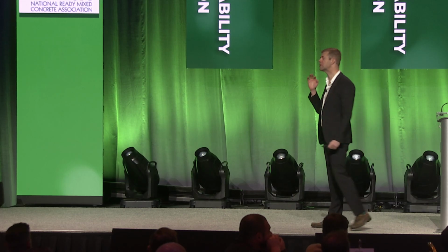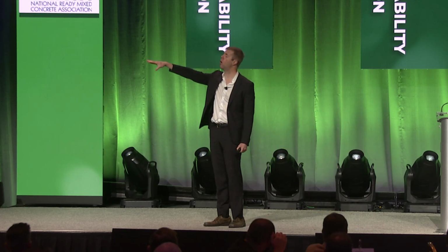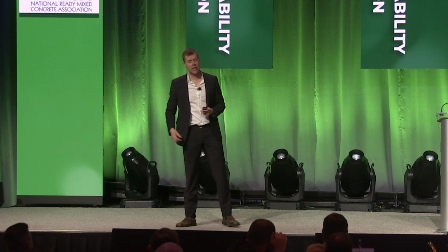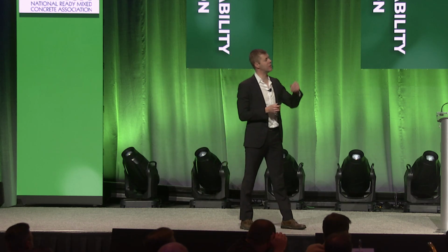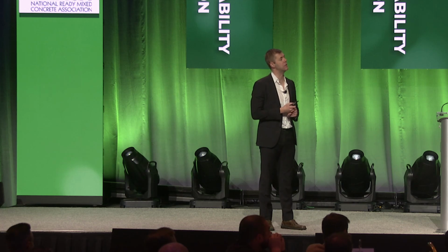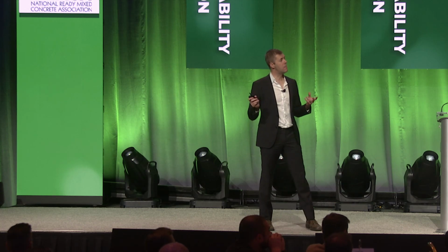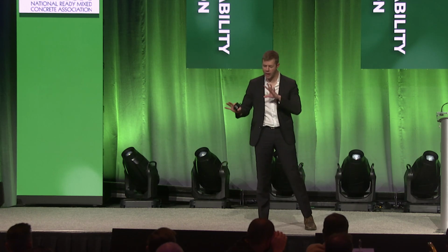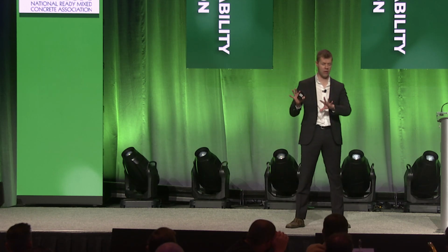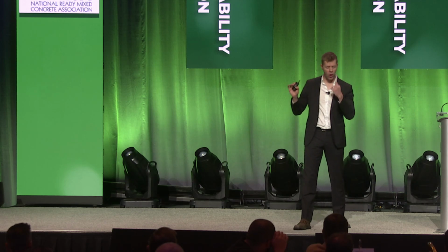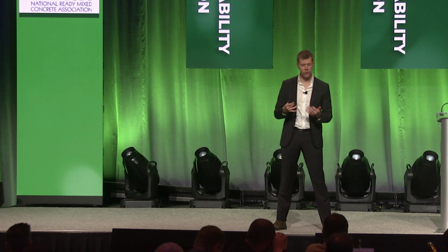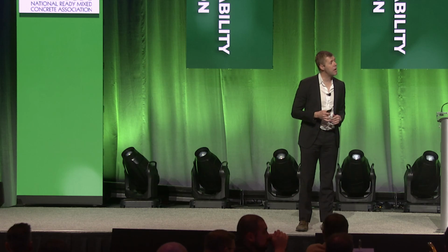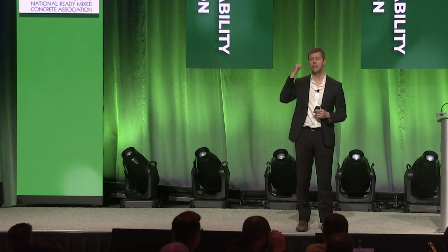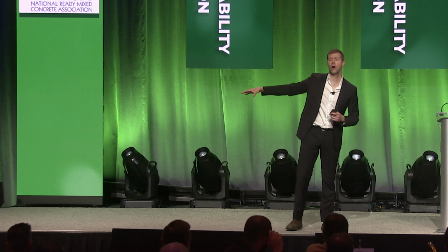And as the truck was leaving, I said, whoa, whoa, whoa. Could I sample some of that concrete, please? And they did. The first truck came out, specified slump was 7 inches. Slump showed up 9, okay? And I measured it with the Phoenix, or started to. And then they brought out another truck. You know, I'm not part of the spec. I can't get in the middle of everything here. They call the batch plant, they call another truck, they dial another one in, and it came in at 8. Rejected. I said, whoa, give me some of that concrete.